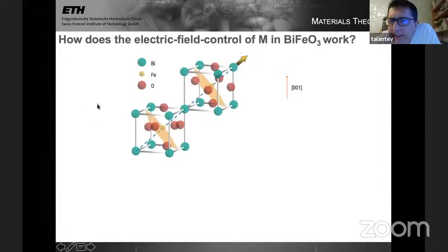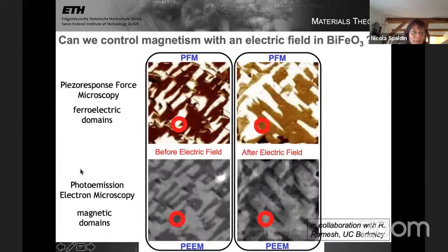So it means that this is not really evidence that it is anti-ferromagnetic, because it can also be ferromagnetic, right? So from these data, the particular way that the PEEM was done, it was sensitive to the anti-ferromagnetic domains. And from other measurements, it's known that bismuth ferrite is anti-ferromagnetic. It's a bit unfortunate. We'd be happier if it were ferromagnetic, but it's not.